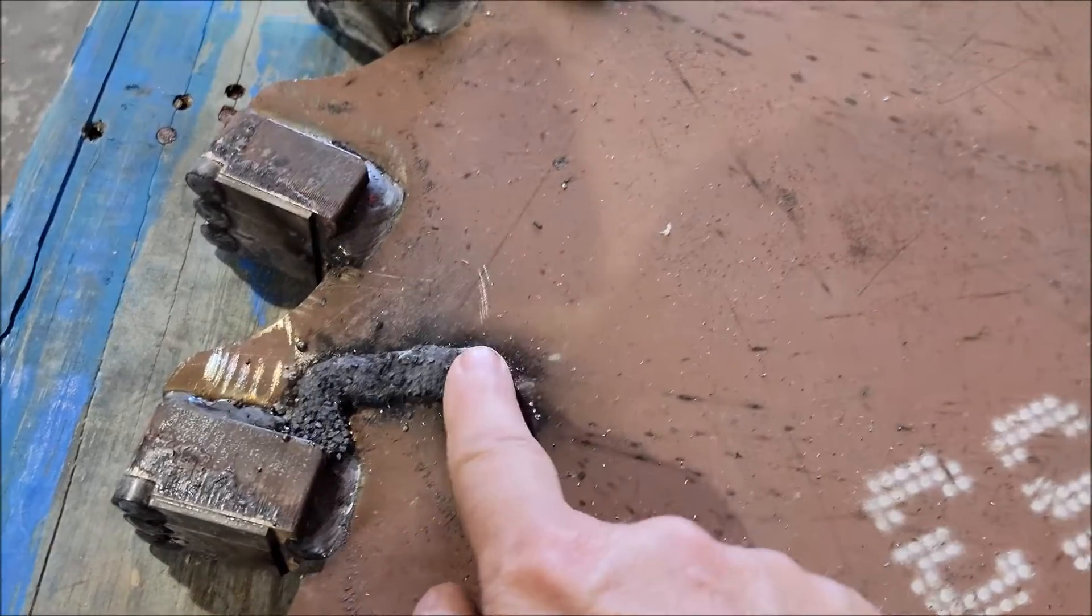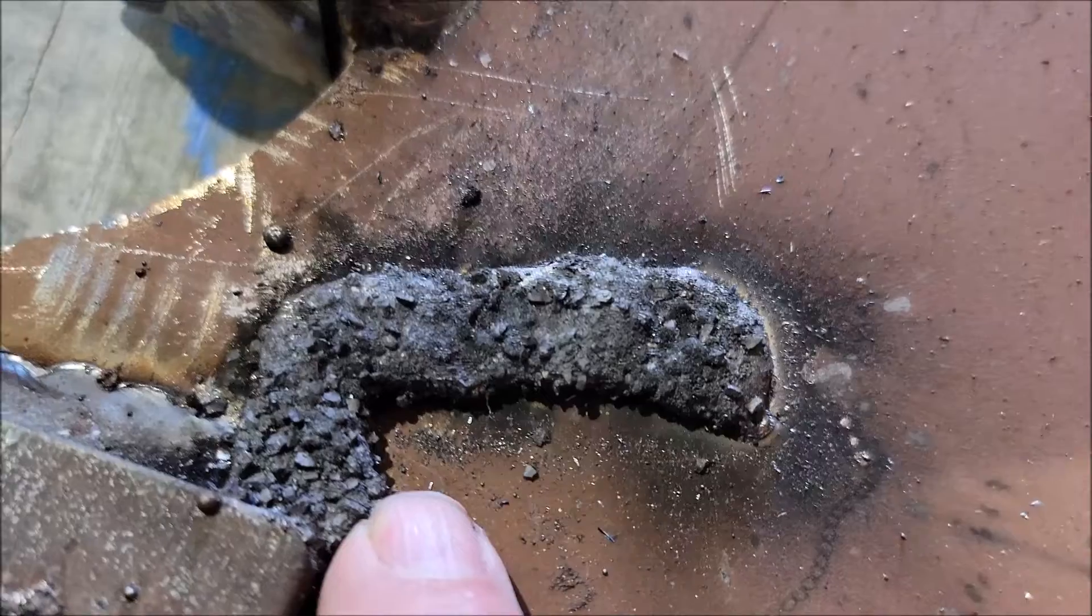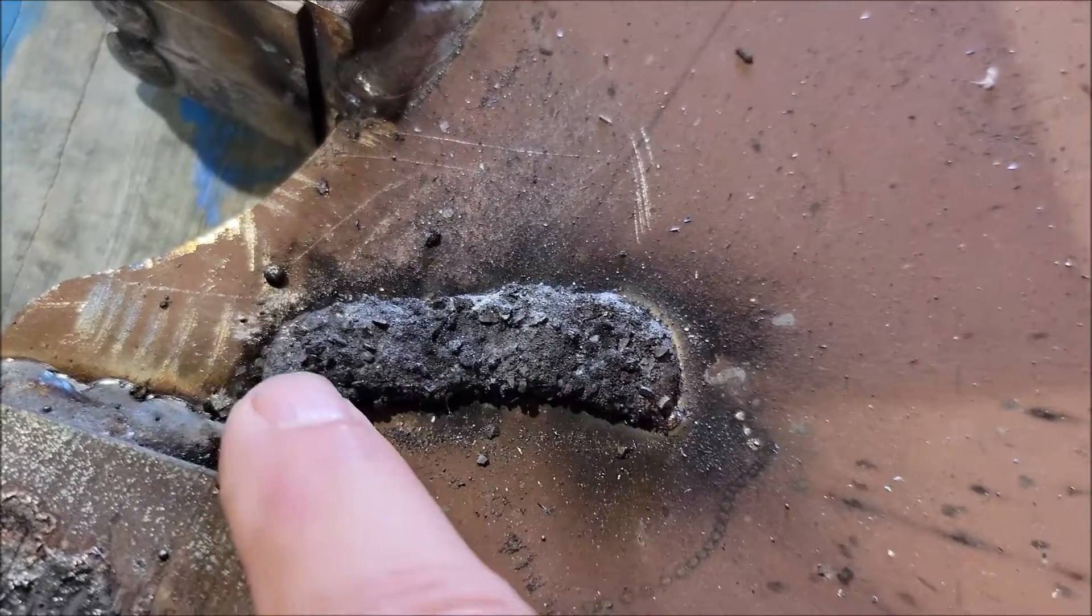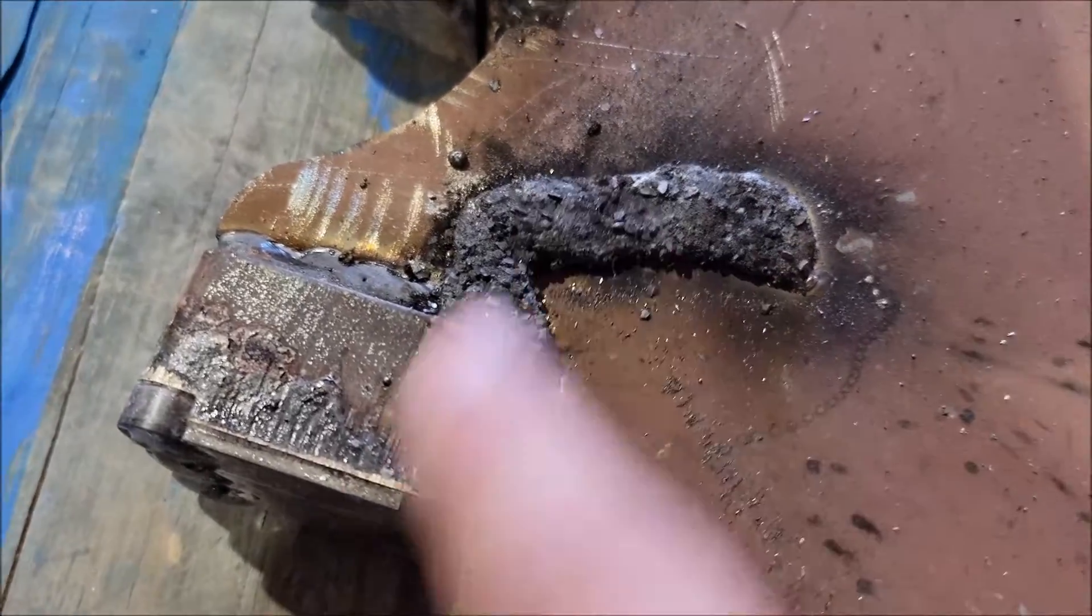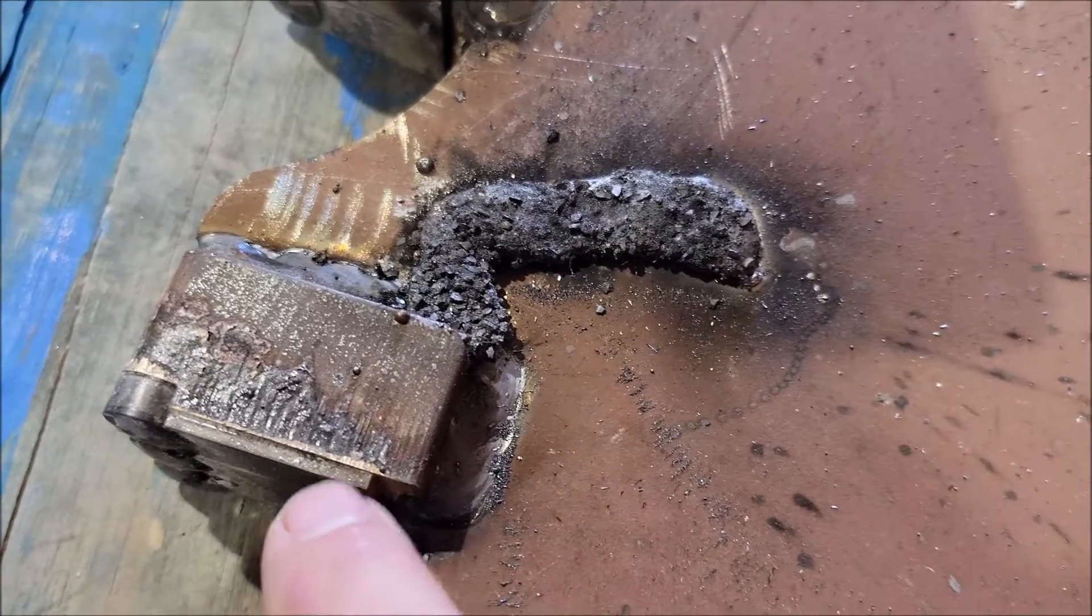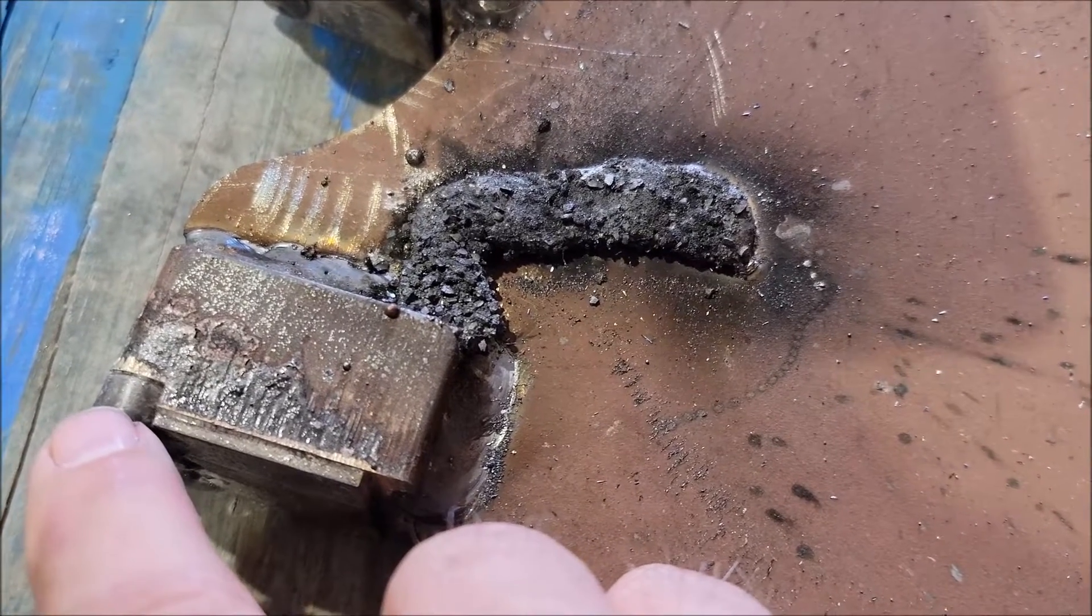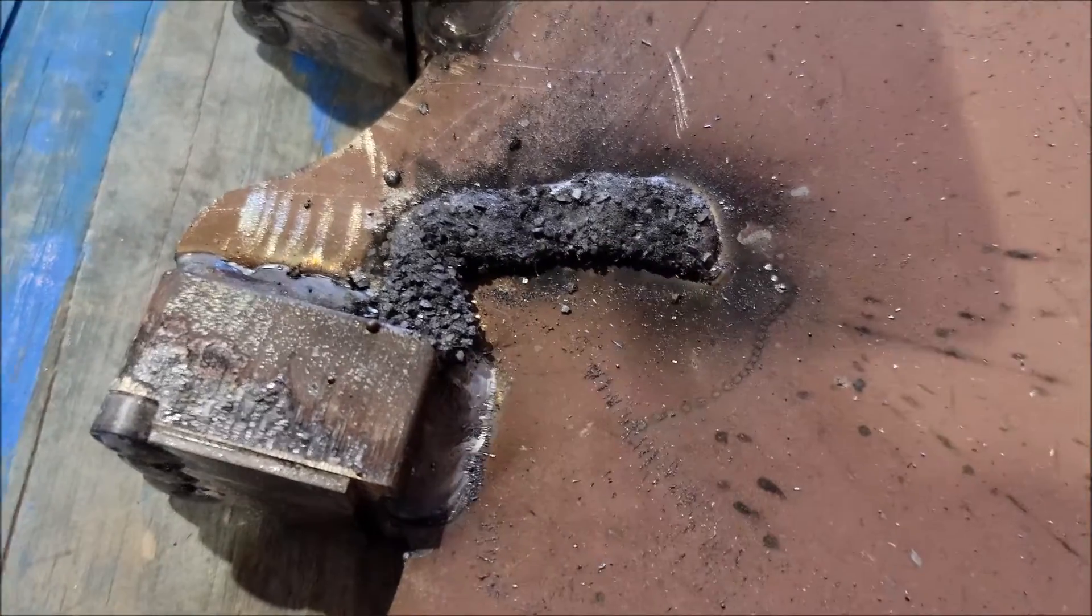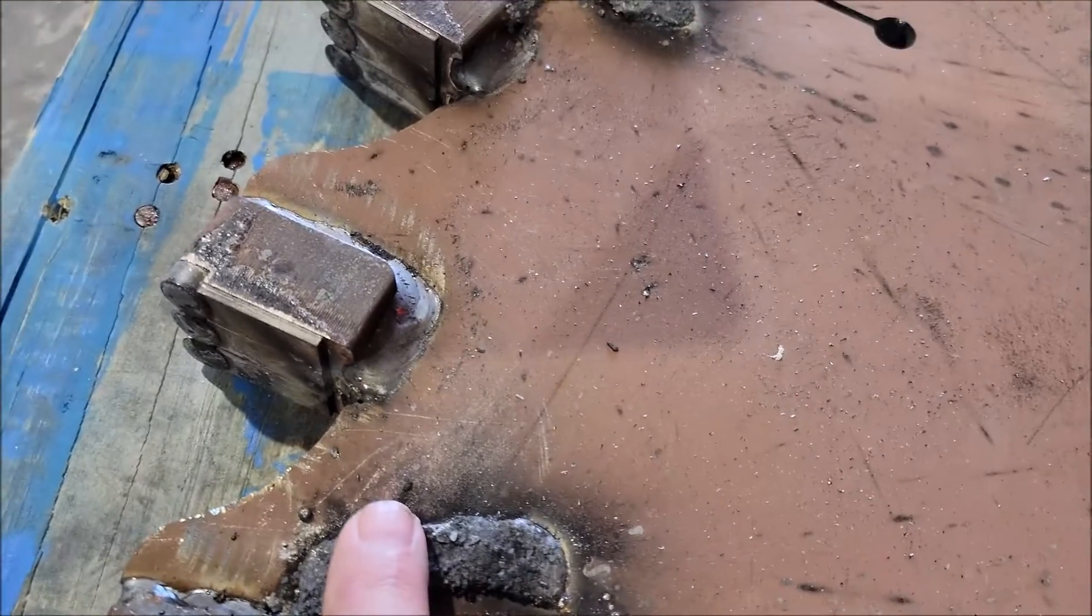So you can see we use a special hard face here. I've talked about it before. It's actually got tungsten carbide grit embedded in the hard facing rod or wire we use, and it's throughout. That stuff's just as hard as the tungsten carbide plate that's here, and the diamond is this little region on the outer edge. It's almost as hard as diamond, but when it wears out in this one area that we keep talking about, it's so critical.